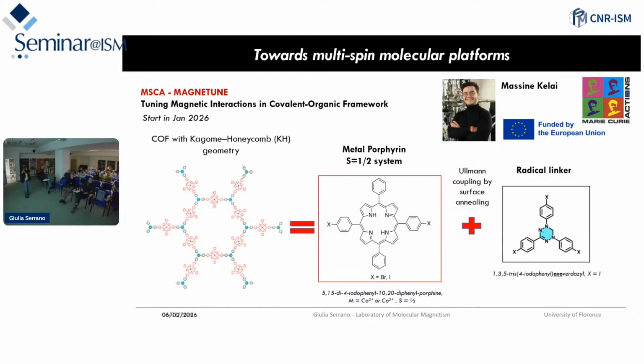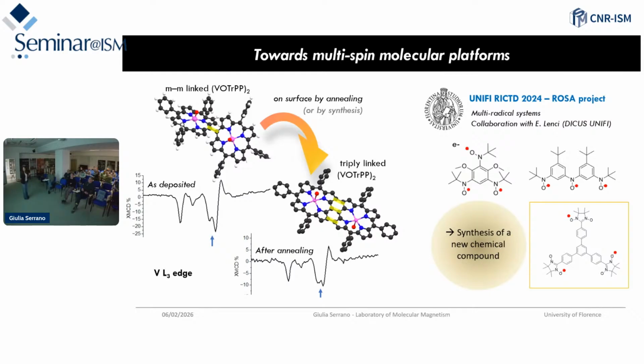Then of course we did a lot already on board, so quite confident concerning the deposition of porphyrins. But we are going to study if we can couple this single object to the Verdazyl, and which is the success rate. The additional challenge for me is to really couple magnetic spins in the porphyrins through this channel, because ions in porphyrins can barely couple in this configuration. So this vanadyl species has a magnetic exchange interaction which is in the order of a fraction of meV. So it's very weak, but it's really good for doing CZ gates, so quantum logic gates. So it's good for that purpose.